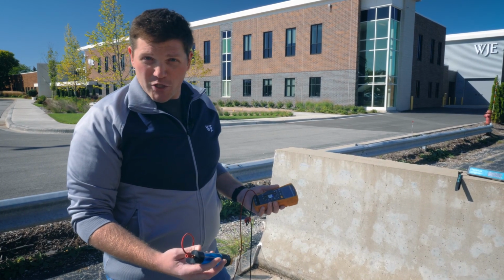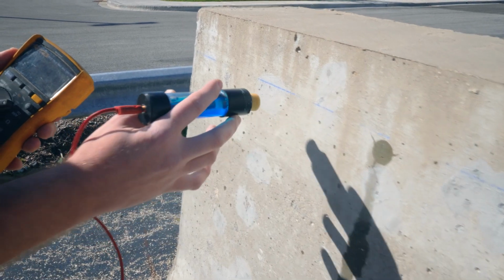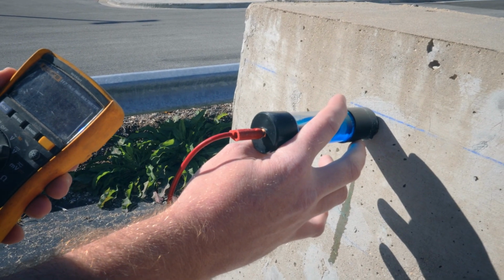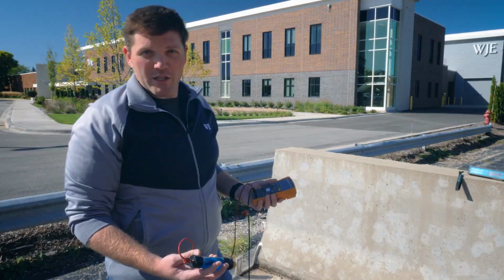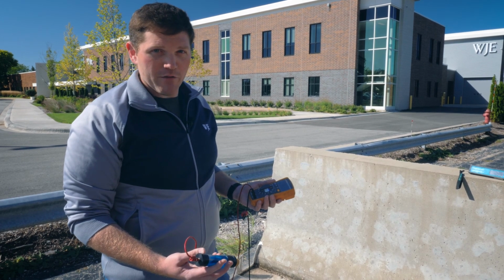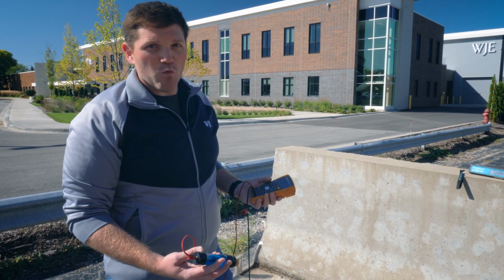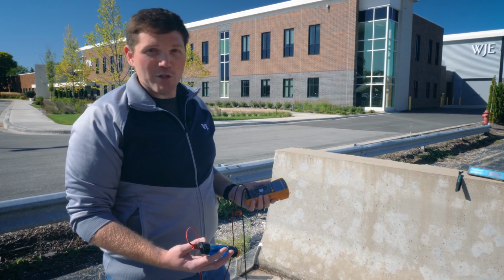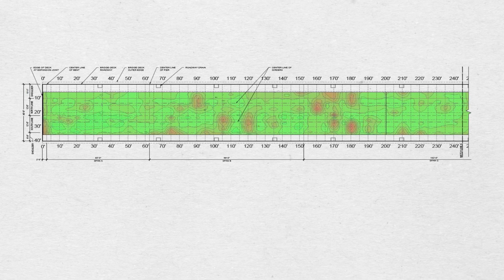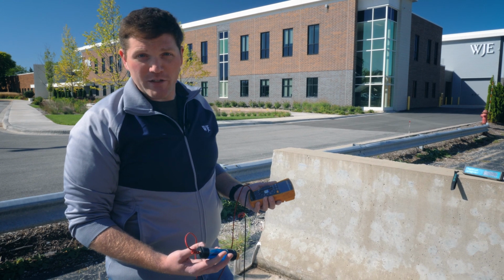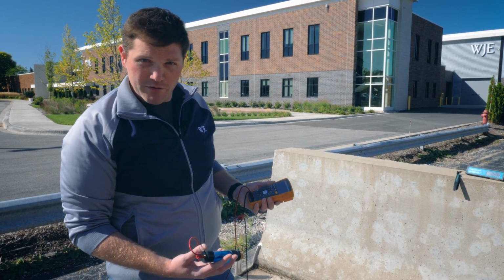We typically take measurements in a regular spacing across the structure, and then the changes in voltage that we measure is correlated to the corrosion activity of the embedded reinforced steel. We'll take these data and plot them in a contour plot, and that'll give us indications of hotspots of potential corrosion activity in areas where we might want to follow up with additional inspection or potentially repairs.